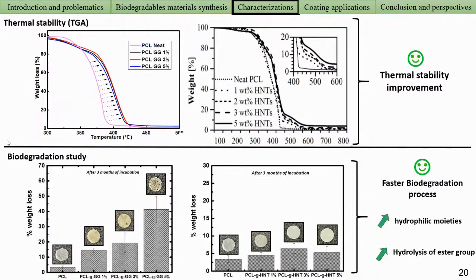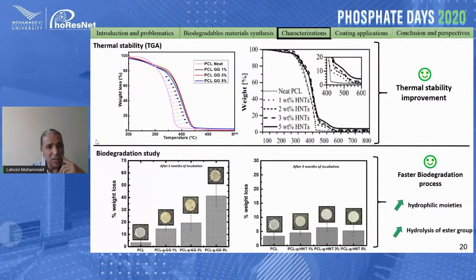But for biodegradation of the materials in soil, we observe that the more fillers we have, the faster the degradation of the material. This is because the filler is hydrophilic, so it absorbs water. And as we have an aliphatic polyester, water reacts with the ester, so we hydrolyze, and this facilitates its decomposition or biodegradation. So we have a good material. Normally, it's intended for packaging and also for coating of fertilizers.